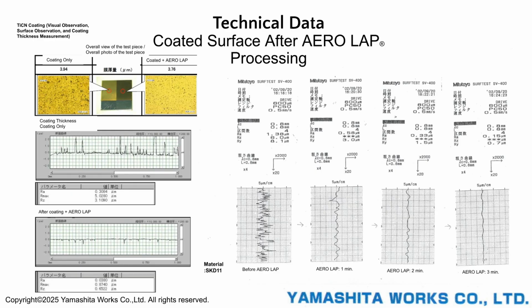Next, please look at the data below. These results were measured by physically contacting the surface with a contour tracer. On the surface without Aero Lap processing, the waveform rises sharply in some places. This indicates droplets, which are large particles formed when ionization is insufficient. When finished with Aero Lap, these protrusions are removed, resulting in a nearly flat and smooth surface.